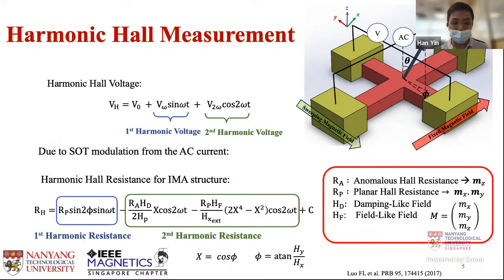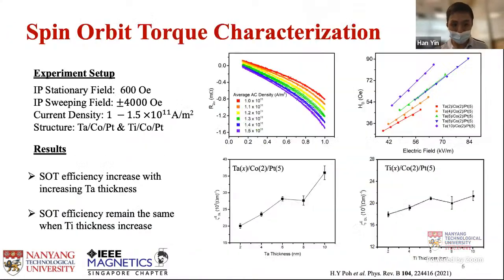So in the IMA sample, the Hall resistance can be written in this form over here, where RA is an anomalous Hall resistance, which is proportional to MZ. RP is a planar Hall resistance, which is proportional to the dot product of MX and MY. HD and HF are the damping-like field and field-like field respectively.